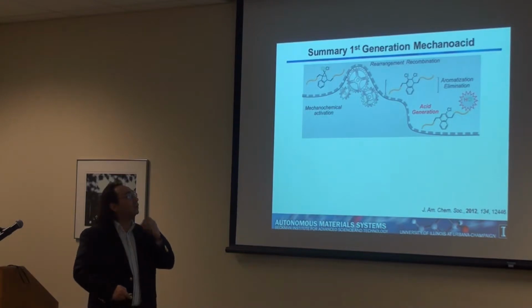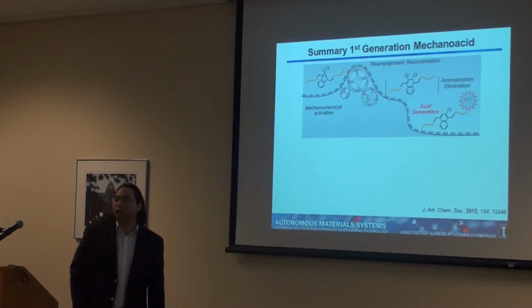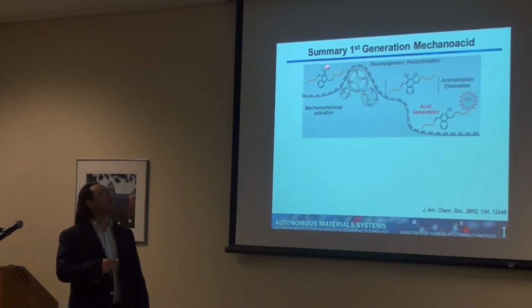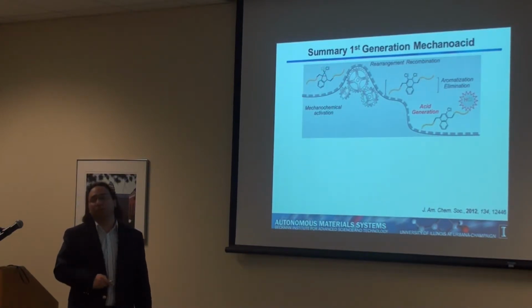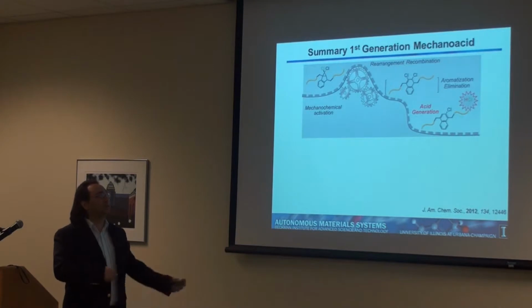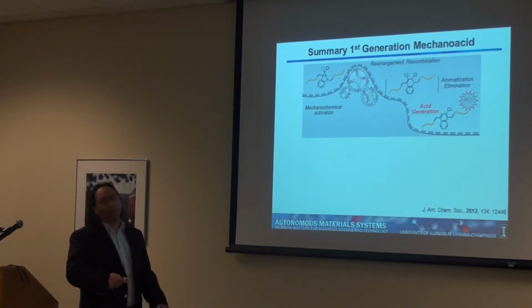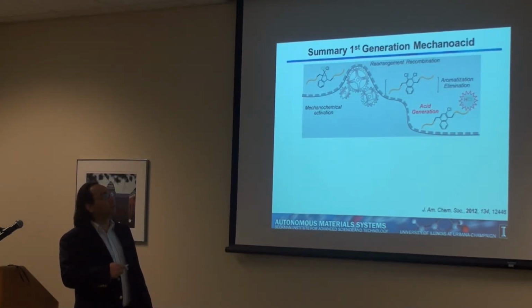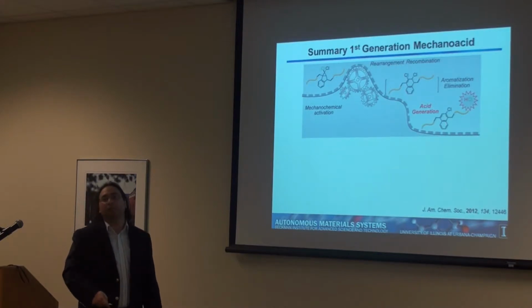So basically that's our first generation mechanoacid. We basically incorporate this into the polymer. We apply mechanical force. It undergoes this rearrangement that was demonstrated before, and then just thermally it undergoes another reaction producing the acid that we wanted.